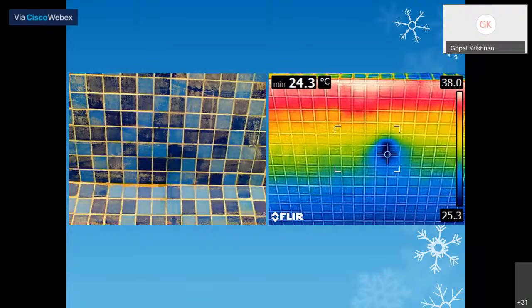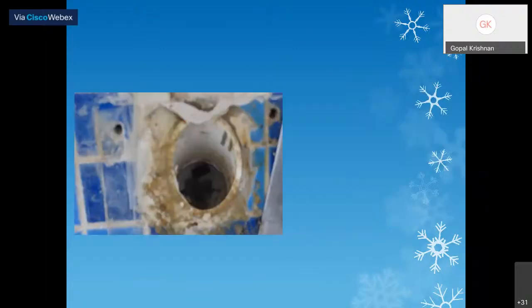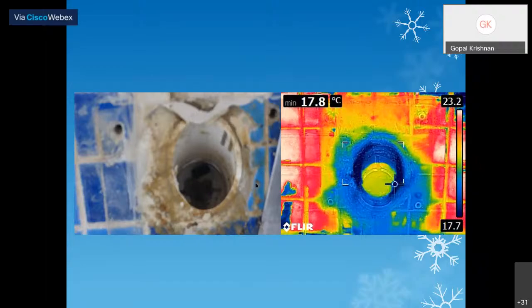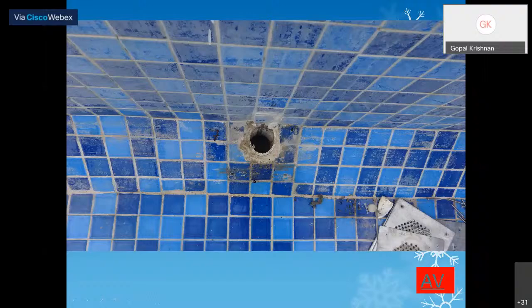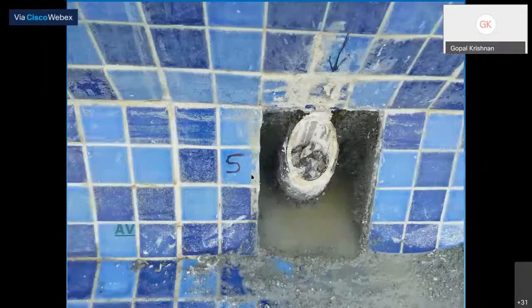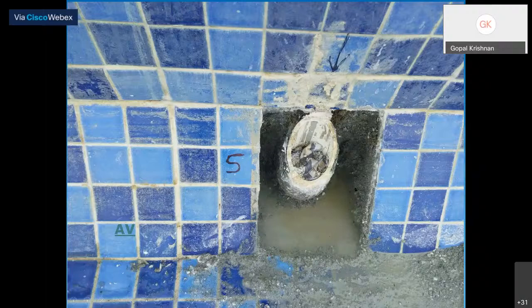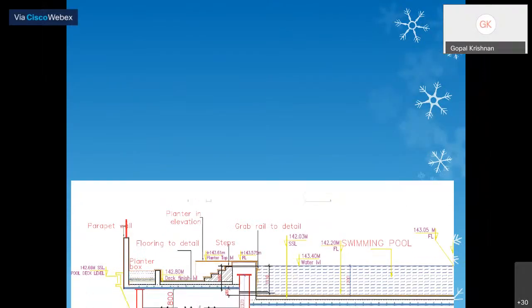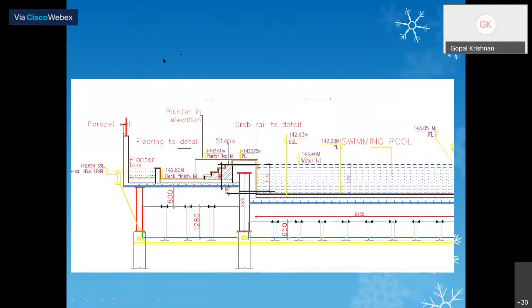So you can see that, there is water. It's returning back whatever entered when the swimming pool was filled. When you do that, it returns back because of the pressure. Finally, after understanding the drawing and the pipelines and everything, I found the damages, where the problem is. This was identified as the source of the leakage. Once we did the repair on that particular area, the leakages stopped completely.